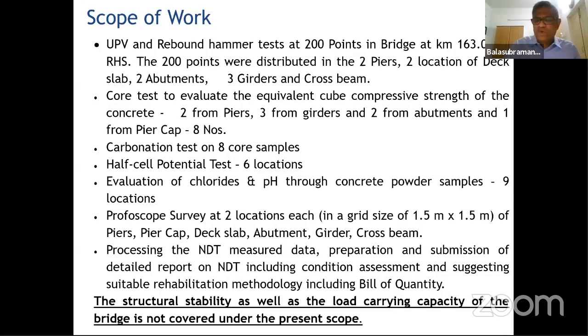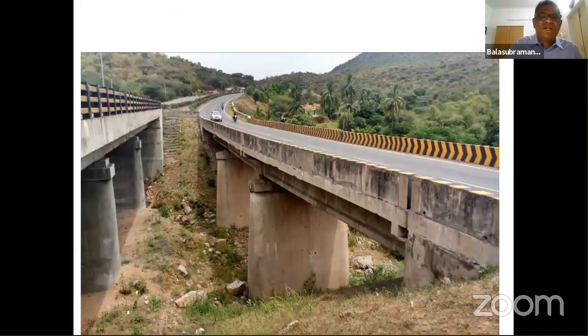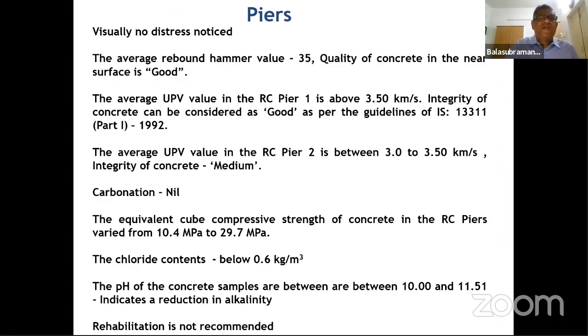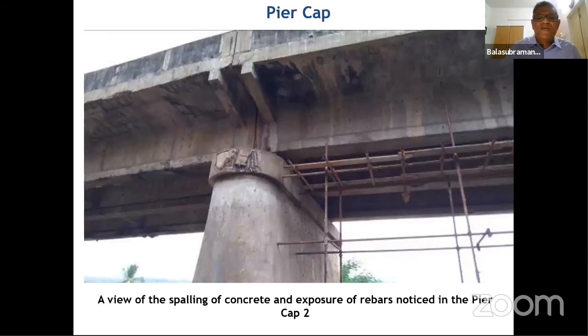So this is the scope of work, and this is a bridge on the Chennai-Bangalore highway. Piers, we didn't have any issue. We did all those tests, whatever. I don't want to repeat it. We did not recommend any rehabilitation. The piers were perfectly all right. The pier cap, there was some issue. So we had gone for a dry spray mortar because this bridge is still in operation. Large containers move on the top of the bridge, and we cannot stop the traffic. So if you have to give some microconcrete jacketing and all that, then you have to put a core through the deck slab.